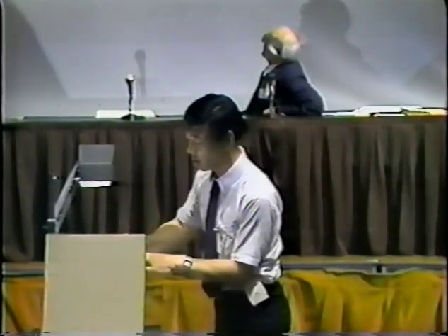Then if you put this in the electrolyte, after electrolysis of 9.5 hours, for example, this is for the light water condition, you see the concentration of hydrogen inside the palladium. And even if you do the same thing for lithium OD in heavy water, for some reason hydrogen got into the palladium much faster than deuterium, so you see a lot of hydrogen but a very small amount of deuteron in there. Also, in this case, you see a lot of lithium in there.